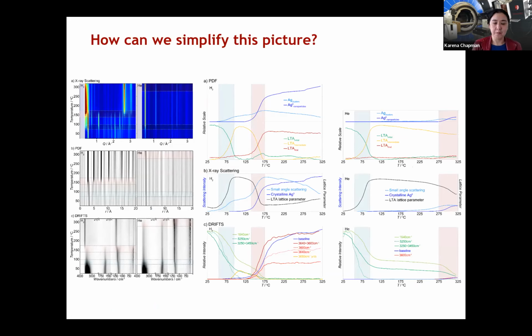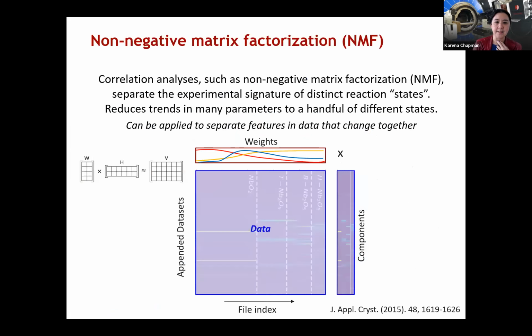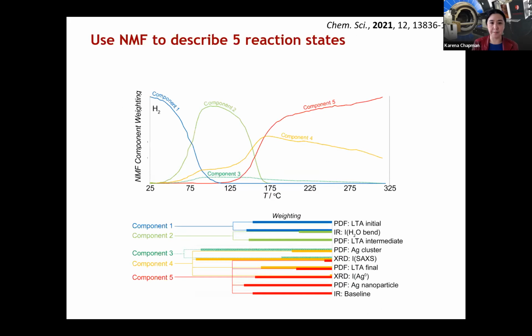And what we realized is we could then take this data and simplify it by using a non-negative matrix factorization, which takes all these conventional analyses and then refactorizes it in terms of a basis set that represents the distinct states within the sample. So we could take all the trends in PDF, XRD, and drifts IR, and we could apply an NMF analysis to simplify it.